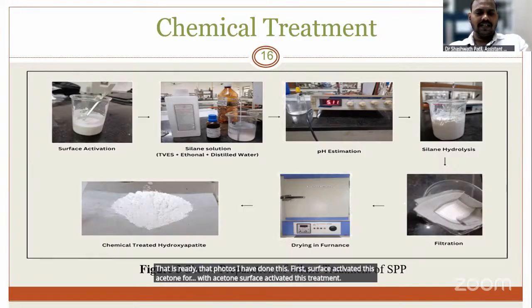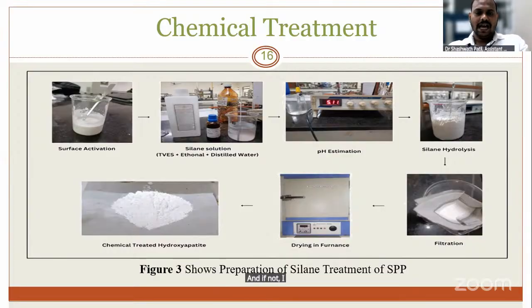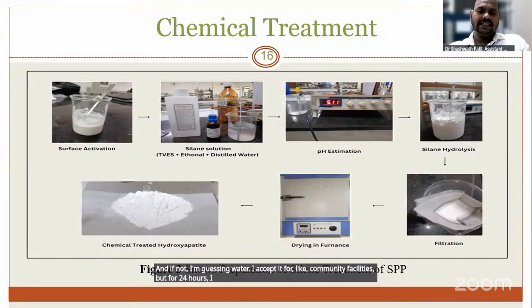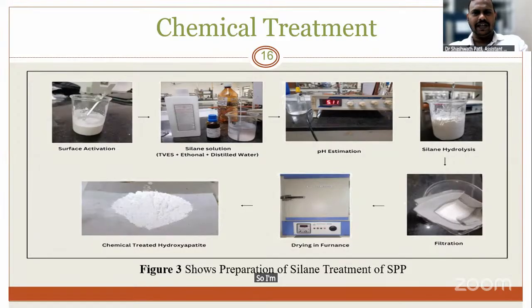Then, after filtering it out, I used the silane solution with TVES solution, ethanol and distilled water, with a pH adjustment. I submerged this powder in the chemical solution for 24 hours. Then I filtered it out and dried it in the furnace for 6 to 8 hours. Then this chemically treated hydroxyapatite material was extracted.